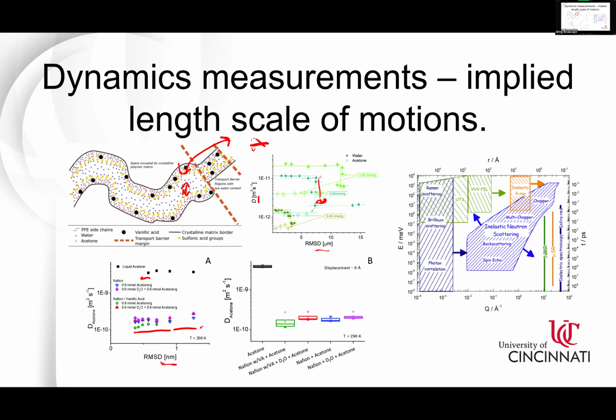But there's an absorption factor and then there's a scattering length and a scattering cross section. And so when you produce a sample for a neutron beam, you're aiming for something greater than 90% transmission. So essentially you have to thin the sample to the appropriate thickness, conscious that you don't want to see multiple scattering events.